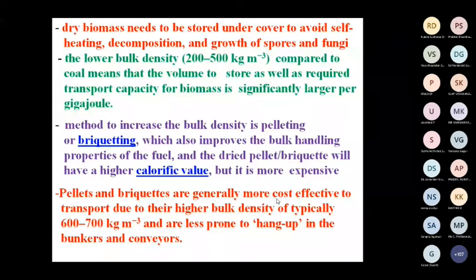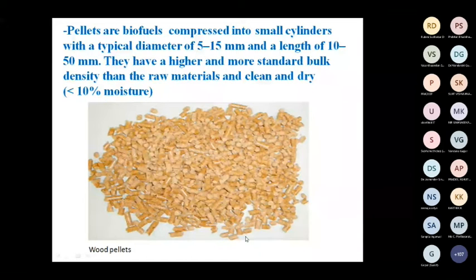See, 600 to 700 kg per cubic metre. From somewhere around 200 to 300, you could make it 600 to 700 kg per cubic metre bulk density by pelletizing. They are less prone to hang up in the bunkers or conveyors. These are the pellets, wood pellets. Pellets are biomass compressed into small cylinders with a typical diameter of 5 to 15 mm and length of 10 to 50 mm. They have higher bulk density, and they are clean and dry, because of pelletizing all the moisture gets removed. The moisture will always be less than 10%, and you can get consistent quality.